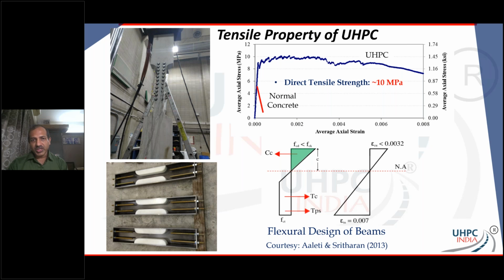If you look at the top diagram on the screen, UHPC is a very, very ductile material. So it is not brittle like normal concrete. If you look at the red line, that's for normal concrete, and you see the brittle nature of normal concrete in tension. Basically, in tension, it just comes apart. But when you look at UHPC, you see how ductile it is, and you get really good strain hardening behavior out of it.